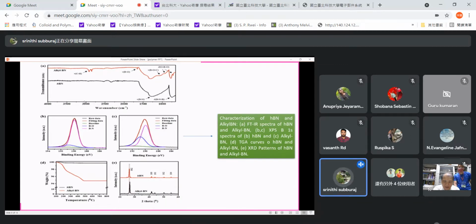So the B-O stretching, out-of-plane bending, and in-plane bending vibration modes have been demonstrated respectively. So this is an XPS analysis performed to investigate the chemical state of elements and their ratio. It shows the XPS spectra of HBN and alkyl BN respectively.